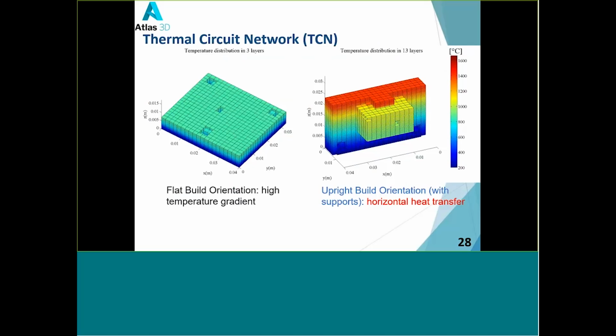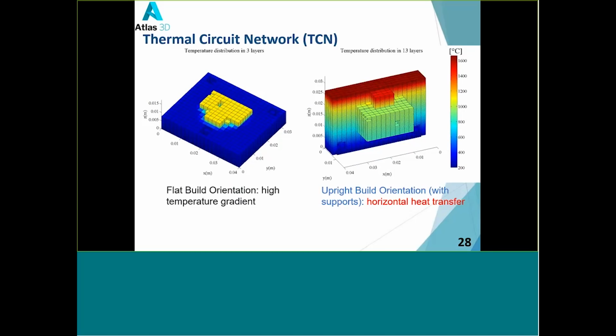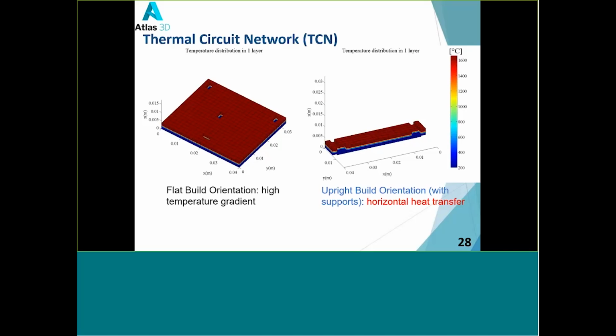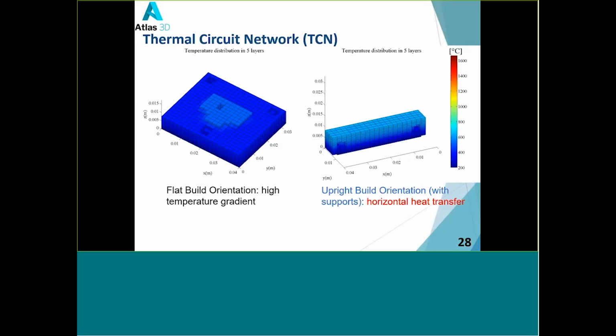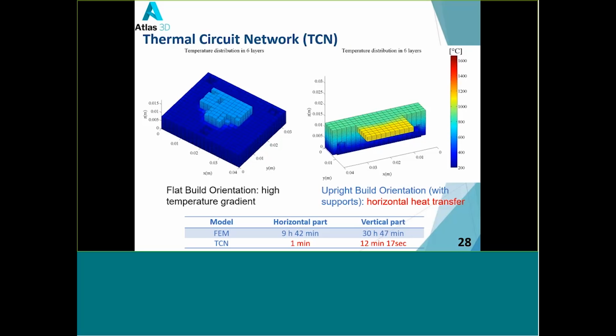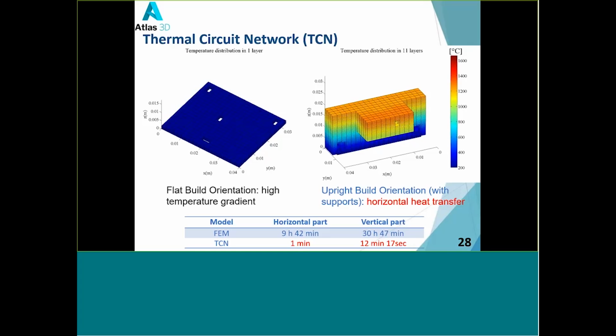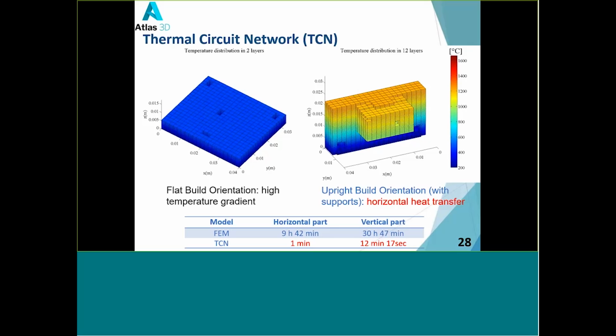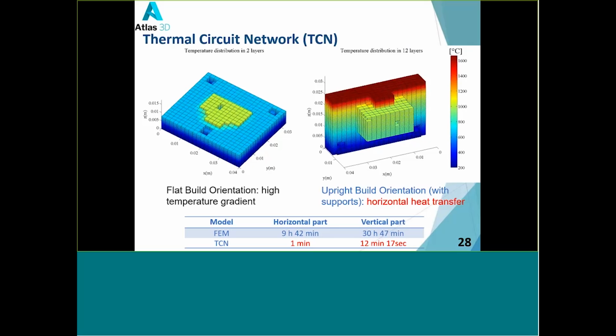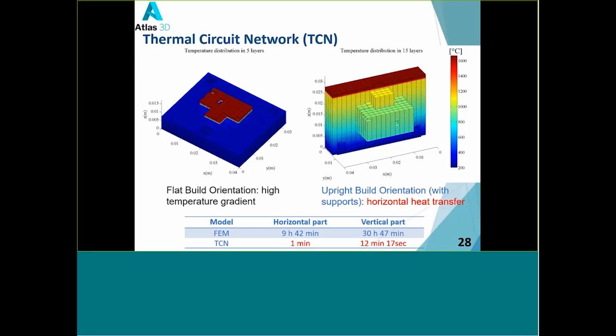And when we build the part vertically, we need support structure over these overhanging features. I didn't show it here, but we include that in our simulation. And you can see how heat transfers from the overhanging area, because it's hotter. The good thing about the TCN, or thermal circuit network, is that it's very efficient in comparison to finite element. We modeled the same process with finite element and it takes 10 hours and 30 hours for the horizontal part and the vertical part. But for the TCN, it takes only 1 minute and 12 minutes, much more efficient.